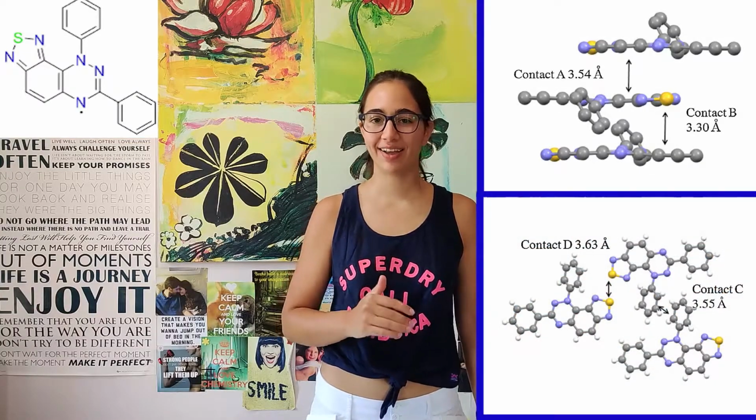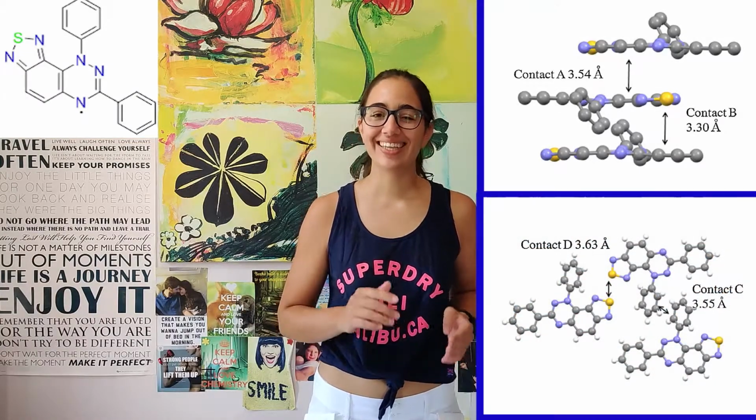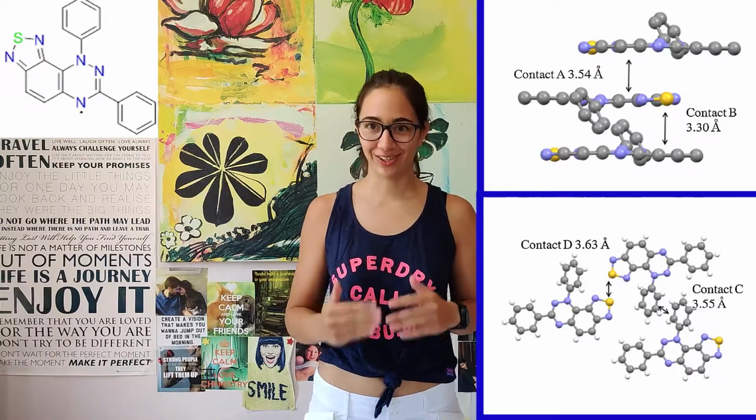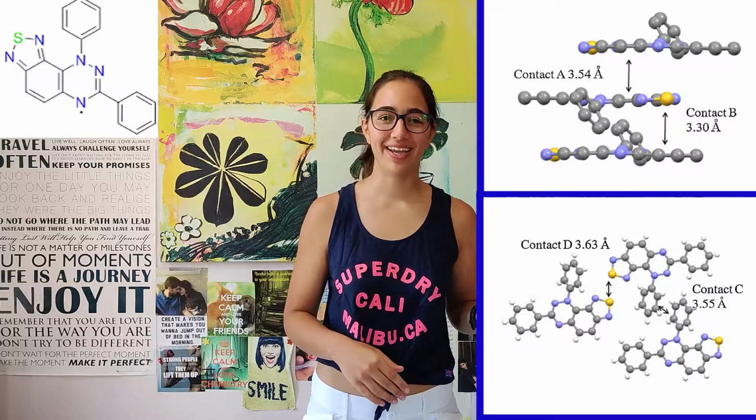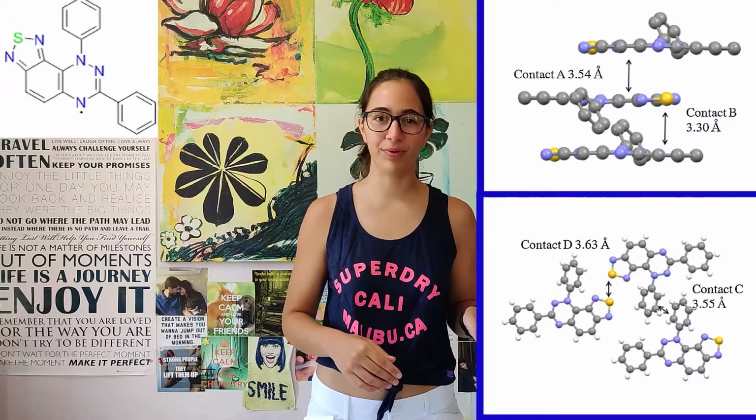The first one is that of a Blatter radical containing a 5-membered 2,1,3-thiadiazole ring. The spin density of this system extends to the entire thiadiazole system and is not localized on the benzotriazinyl ring. These molecules form dimer structures and a slip-stack column structure by stacking the dimers in the crystal, as shown. It is this pi-stacked structure and pi-pi interactions that result in the magnetic properties observed.